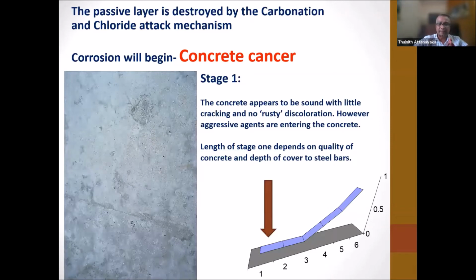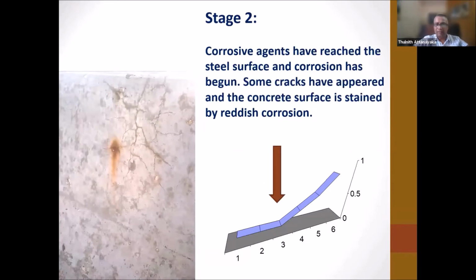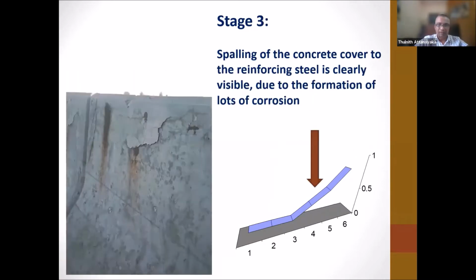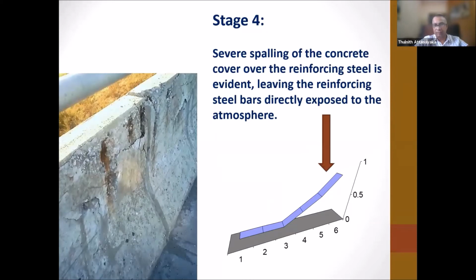Stage 1, you can see on the slide, you can't see any visible crack or corrosion spot. It's a slight discoloration in the concrete, but this is stage 1. So stage 2, after some time, the corrosive agent has reached the steel surface. In the previous slides, you have seen the front has already touched the steel bar. Then you can see a slight small patch of corrosion, a reddish corrosion patch. After some time, spalling of the concrete cover to the reinforcement steel is clearly visible. Now that is stage 3. Of course, this is stage 4. The severe spalling of concrete cover over the reinforcement steel is evident.